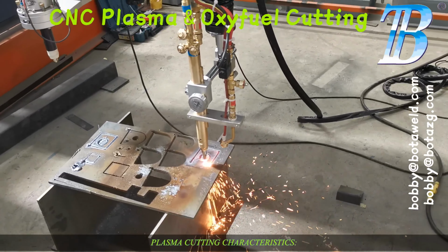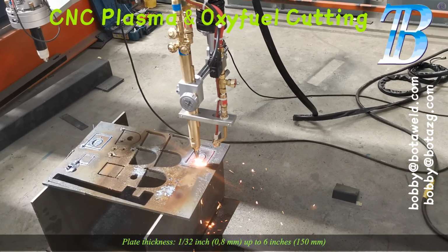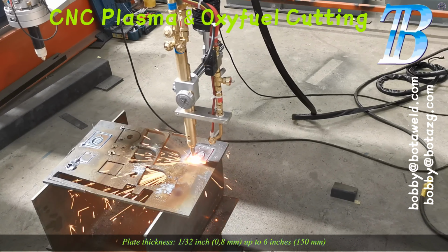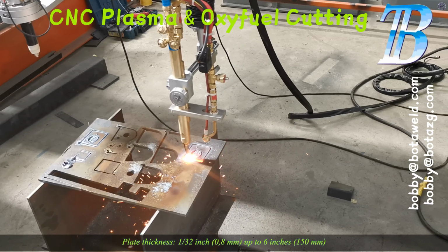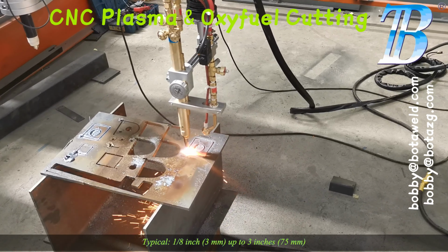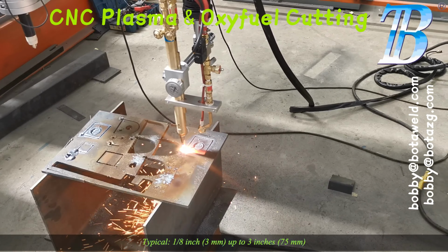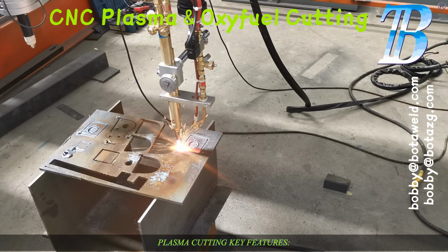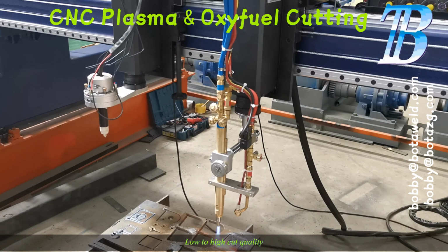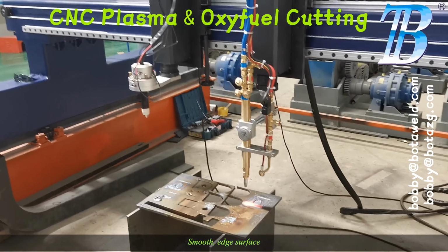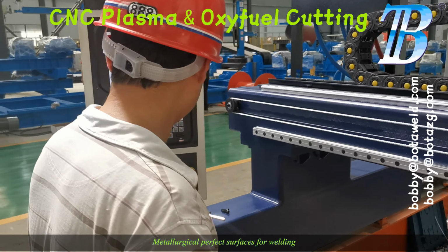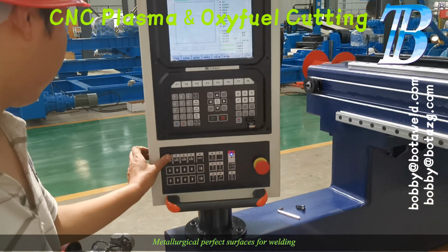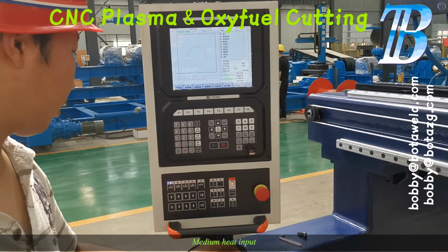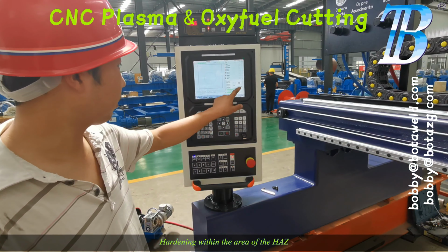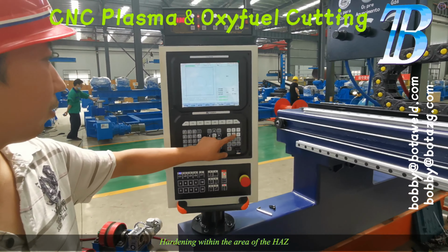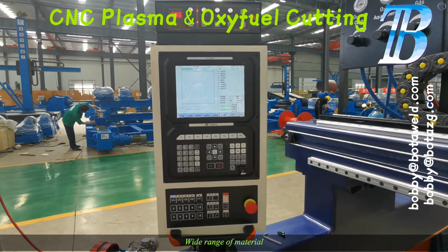Plasma cutting characteristics. Plate thickness 1/32 inch (0.8 mm) up to 6 inches (150 mm). Typical 1/8 inch (3 mm) up to 3 inches (75 mm). Plasma cutting key features: low to high cut quality, smooth edge surface, metallurgically perfect surfaces for welding, medium heat input, excellent cutting speed, hardening within the area of the HAZ, wide range of material.